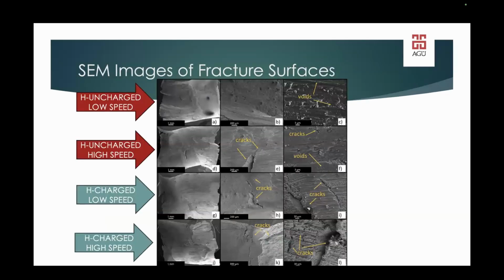And yeah, like hydrogen uncharged specimen at low speed, we came up with some voids. And for hydrogen uncharged specimen, we kind of observed deep cracks, some moderate cracks with some dimpled surface, but hydrogen charged specimen, we have bigger cracks, deeper cracks, and more like cleavage facets.